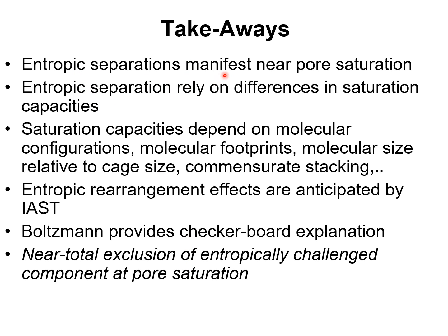Entropic separations manifest near pore saturation. Entropic separations rely on differences in saturation capacities and packing efficiencies. The saturation capacities depend on molecular configurations, molecular footprints, molecular sizes, etc. It's important to note that the entropy effects are anticipated by the ideal adsorbed solution theory.